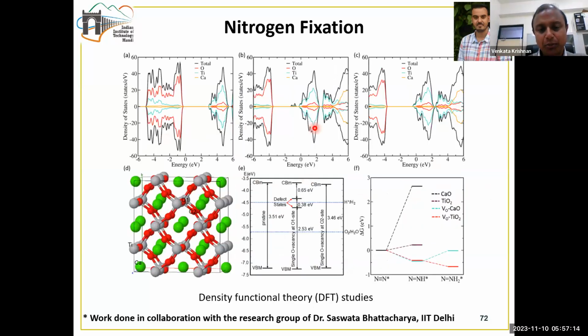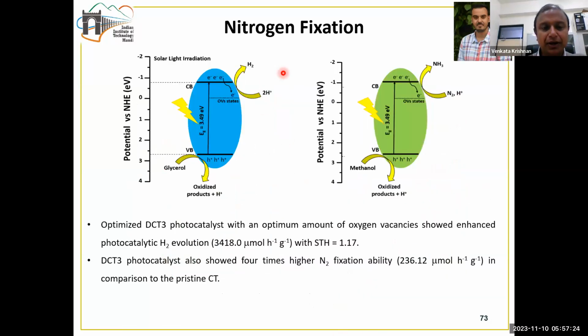We also did a detailed theoretical analysis of the reaction using density functional theory, in collaboration with the group of Dr. Saswata Bhattacharya from IIT Delhi. We came up with the possible mechanisms, first for hydrogen evolution, because the same catalyst is effective for both hydrogen evolution and nitrogen fixation. So we worked out a plausible mechanism for hydrogen evolution, and a possible mechanism for nitrogen fixation.